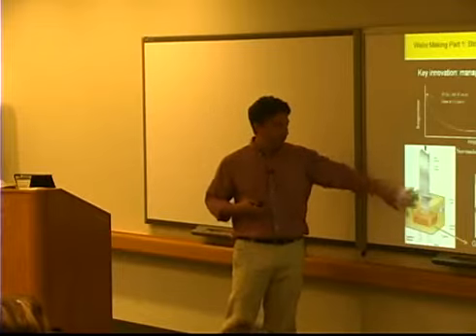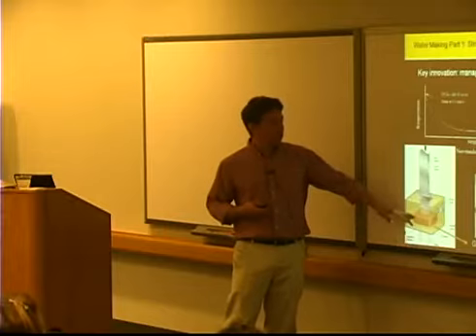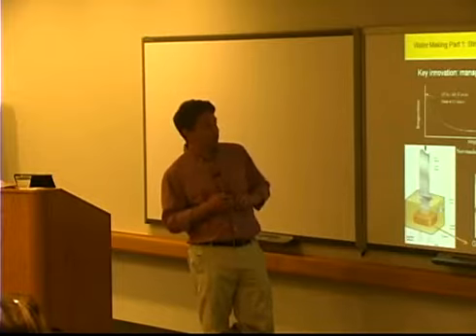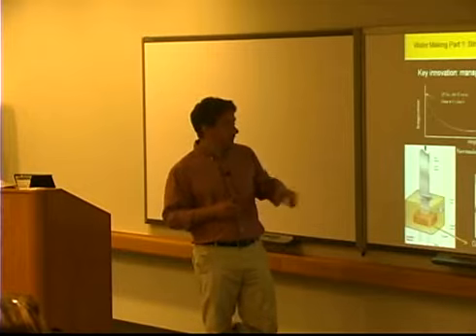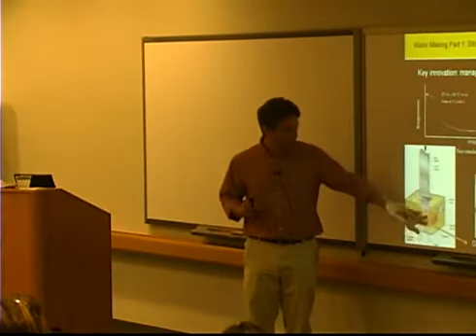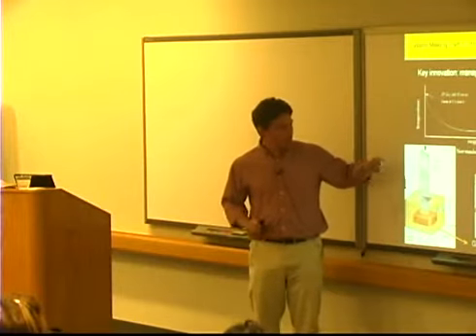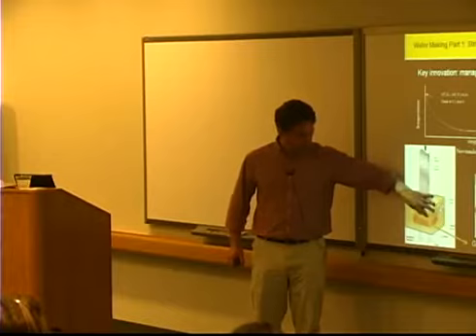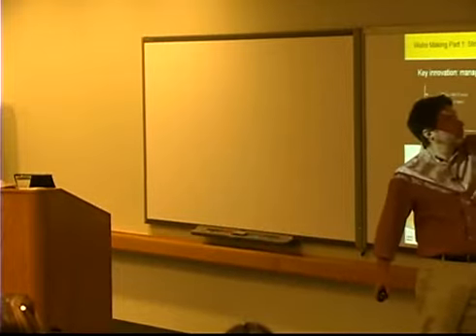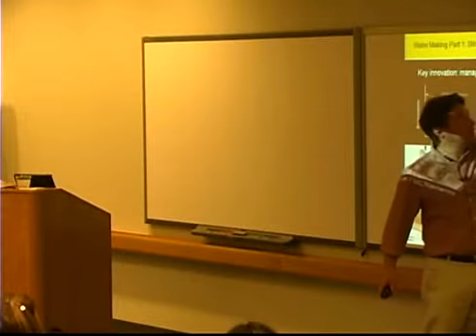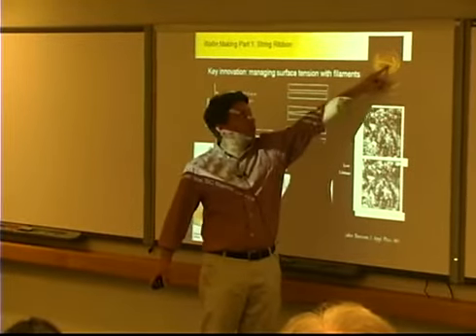So motivated by that, we're going to start with the freezing silicon methods that try to go directly to a wafer format. This is string ribbon. It was originated by Ted Ciszek at NREL and also Ellie Sachs, who's got the company that I worked for in Massachusetts. And the way it works is that you bring two filaments of string, typically graphite or silicon carbide, up through the bottom. There's two small penetrations in the bottom of the crucible here into a melt of silicon, and then you start with a seed crystal of some sort between these two that then pulls up a meniscus. And so here's a picture of the process actually happening. It's a little dark, but here's the wafer coming out of this small pot of silicon. The liquid down here looks relatively dark, again, because it's low emissivity.